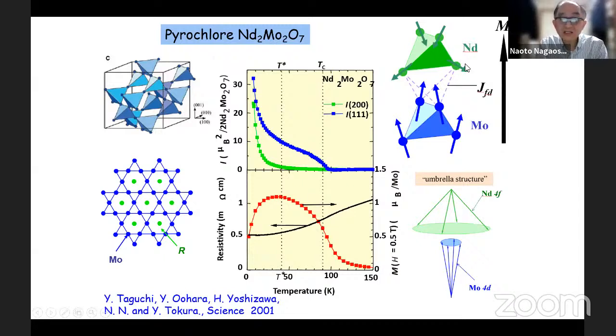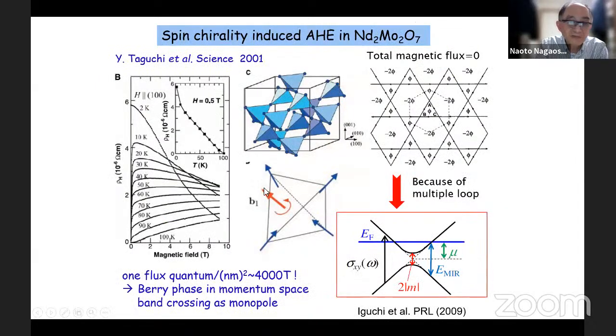Then these neodymium spins are coupled through the exchange interaction with the molybdenum spins. This is the conduction electrons, and this is the localized spins. So this leads to a small tilting, canting, of these molybdenum spins, which is moving. And then this leads to an effective solid angle for these molybdenum conduction electrons. Then most naturally, this leads to a gauge flux coming from this spin Berry phase. And this one is observed experimentally as a function of temperature and magnetic field.